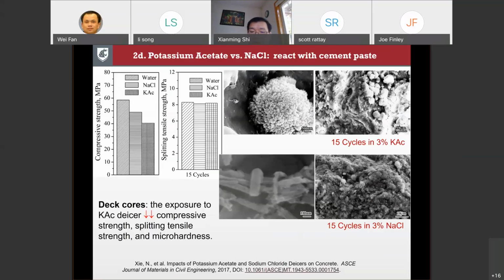So what's happening is basically the concrete was losing calcium and then forming new crystals. The calcium leaching behavior basically makes the concrete weaker and it's compromising the gel which holds the concrete together. It's very similar to when humans age. When we age, we lose calcium and our bones get brittle. So this is a very similar phenomenon and very concerning.